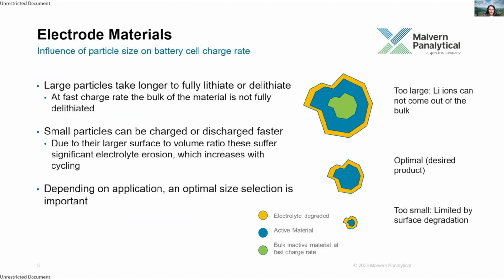The particle size will be an important factor in how quickly you can charge the material and how effectively the particles will charge. So at the top, we have an image of a large particle where the different colors represent the active material, which is in blue, the bulk material, which may be inactive at a fast charge rate, in green, and some electrolyte that's been degraded on the surface in yellow. So if the particle is too large, it may take too long to lithiate or delithiate, and you're not making full use of the material, particularly at fast charging rates.